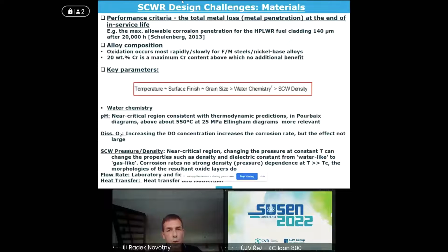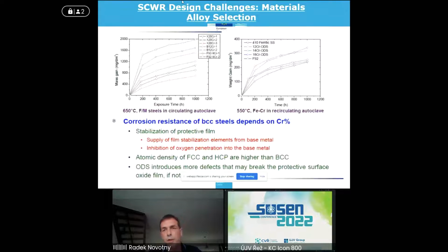If you look at the alloy selection, we perfectly know that ferritic martensitic steels or ferritic steels are much less resistant to supercritical water, even at high temperatures. This is due to lower chromium content compared to austenitic stainless steel. Even the ODS version didn't introduce much more beneficial effect for this. If you look at the results in the upper part, most of the tests we have been doing are corrosion tests. That means we are exposing specimens in the autoclave. We weigh them before and after the exposure, and then we calculate the weight gain due to oxidation. A very simple test.